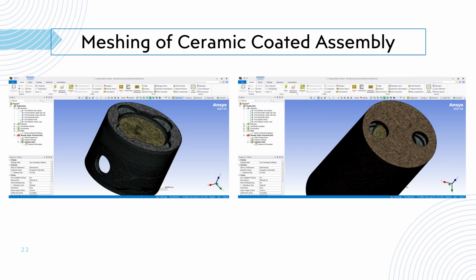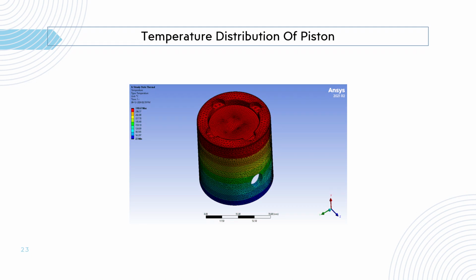This one is the meshing that is done in ANSYS Workbench. This is the temperature distribution of the piston. The simulation results clearly show that the coated piston and the liner surfaces maintain higher temperature compared to the uncoated ones. At the same time, the metal substrate remains protected because the coating absorbs and redistributes the heat stress.